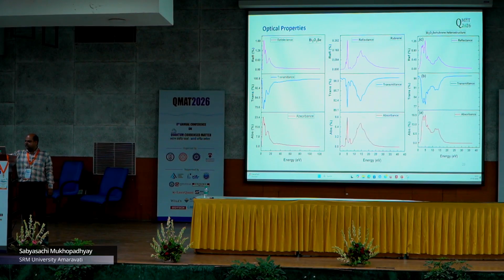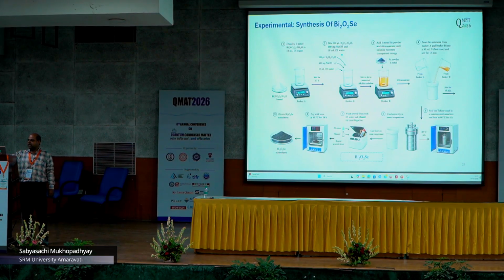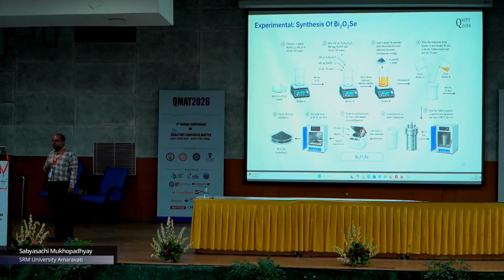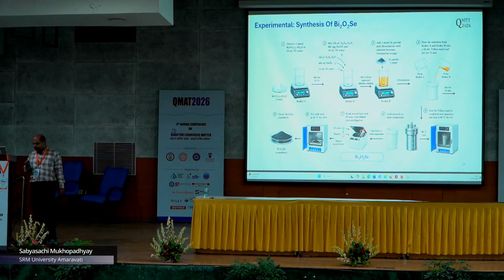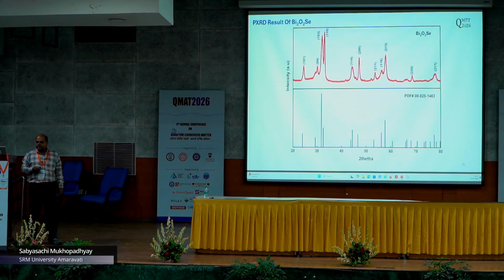So following these calculations, now we have started doing the experimental measurements. We are following the protocol available in the literature to develop the inorganic two-dimensional heterostructure. We started with the precursor, and then during the hydrothermal process, we make those two-dimensional materials, and finally we got nanosheets of the two-dimensional materials. We have done the XRD measurements, and it matches very well with the pattern of what people have already reported for those materials.